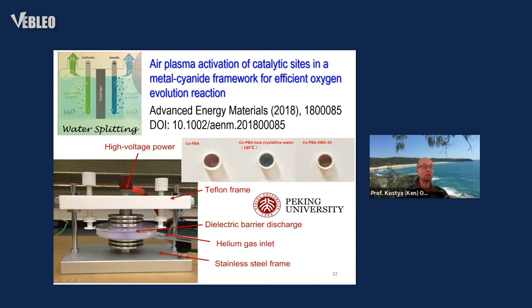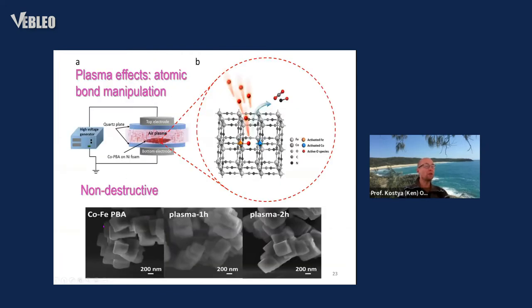So we use this atmospheric pressure plasma reactor and process the material, which is called the Prussian blue analog, which contained iron atoms and also incorporated cobalt atoms. And the iron and cobalt atoms were connected in their three-dimensional atomic network, and plasma was used to process that three-dimensional network. While processing that atomic network, the processing turned out to be gentle and very effective. As you can see, even after 2 hours of gentle plasma treatment, the PBA crystals did not even change shape or structure. So basically the crystalline structure of the crystals was not even affected.